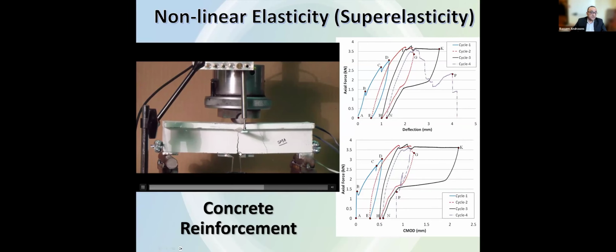See how wide the crack opens? You think it's done, but see when the load is removed and watch the crack, it's closing. That's the beauty about the self-centering or recentering. And you also look here at the CMOD, that's the crack mouth opening displacement. It started taking that nice flag shape hysteresis. Eventually it failed in shear because we didn't design it to have shear reinforcement. But you got my point. So the self-centering has found its way into applications like rebars and plastic hinges for bridge piers, or in moment-resisting frames, or even bracings for seismic frames. And you will find a lot of research in that direction.